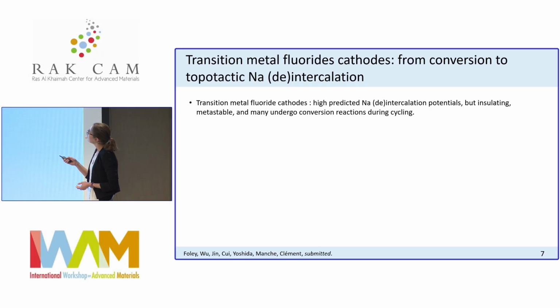And so one of these, the family of interest here, is transition metal fluorides. Transition metal fluorides are interesting as cathode materials because fluorine is a very electronegative element, which typically means that it can raise the potential of sodium intercalation and deintercalation. So you can do this at a higher potential, you can have a higher voltage cathode. The problem with transition metal fluorides, and there are actually quite a few problems, one of them is that they're insulating, they are metastable, and oftentimes they'll undergo a conversion reaction rather than an intercalation reaction. The difference between these two types of reaction processes is that for intercalation, you're not changing the crystal structure, you're simply extracting an ion and reinserting it reversibly. For a conversion reaction, you're breaking bonds, and now your whole material falls apart, and you're making a new material. And these types of reactions are not very reversible.